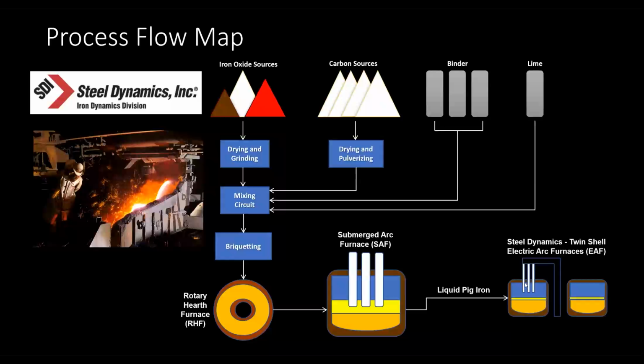In this twin shell configuration, we melt on one side while on the other side we tap the furnace, then do an inspection of the refractory before we add scrap back to it. We put our scrap into the furnace, pour hot metal into it from a ladle, and then it's ready. So when this side's done melting, the other side is fully charged with scrap and ready to melt again.